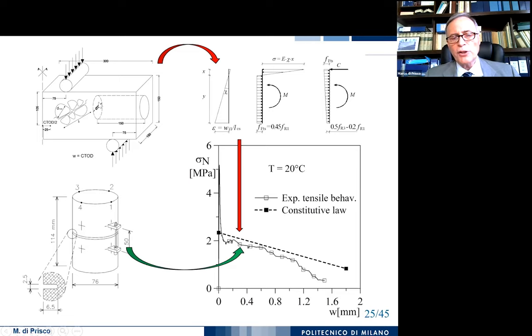We can check by concrete coring on a bending specimen adopted for the identification test. And here you can see what you can obtain passing from the constitutive model. This is a right straight line, dashed, and what you can obtain in a uniaxial tensile test.